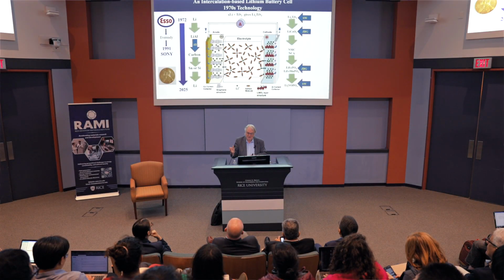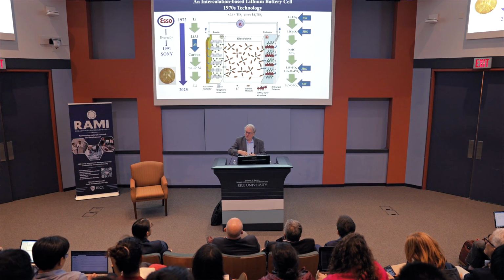On the cathode side, we started with titanium disulfide. You may ask, why titanium disulfide? It's a nice layered compound. All sorts of ions go in there, any electron donors: lithium, sodium, potassium. You can put long-chain ammonium things in there, like C18 nitrogen. And the interest initially was electron donors. They put electrons into the lattice and change the superconducting properties.